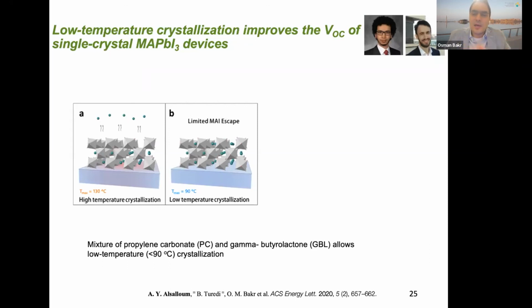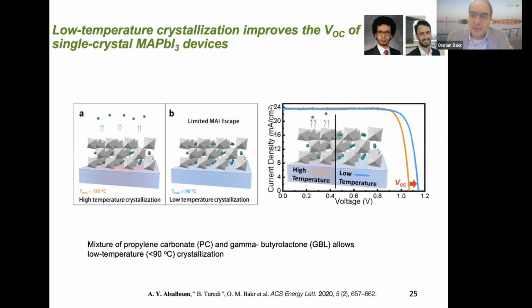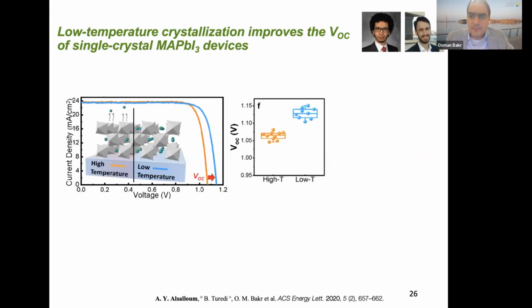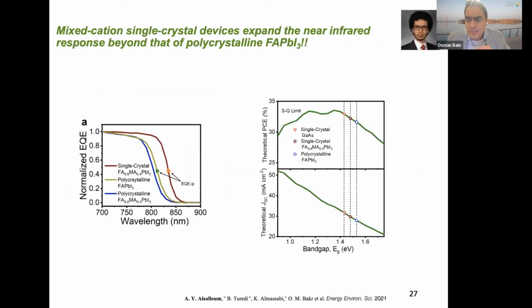We found that by changing the solvents, we could reduce the crystallization temperature, and that would eliminate the escape or degradation of the crystal during crystallization, and that creates a better interface. And we could improve single crystal devices even further, closer to 22%. And we started looking at different compositions, and we wanted to shift the band gap of perovskite solar cells closer to the ideal band gap that you have normally in gallium arsenide solar cells, which have close to ideal band gap for single junction solar cells.